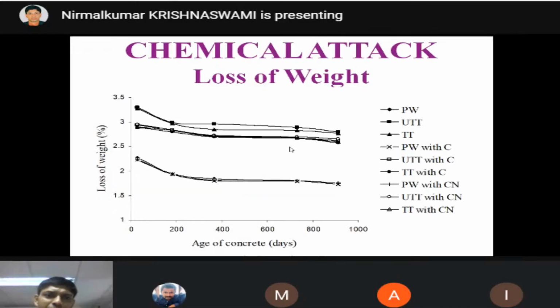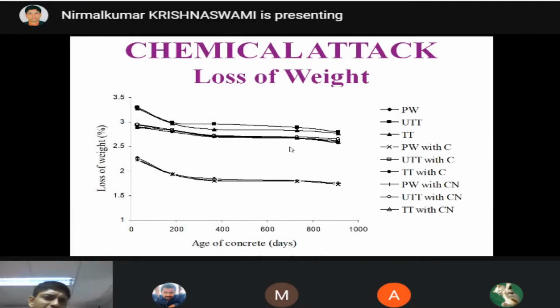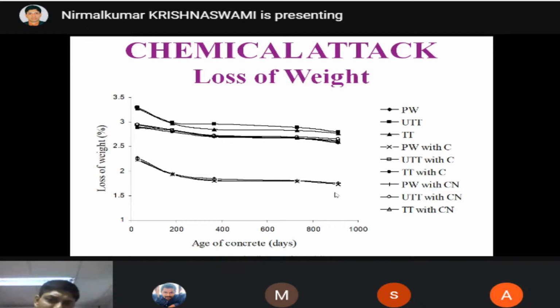And this is for the chemical attack. Here I used 3% diluted sulfuric acid. Then these are all the results. Loss of weight is very high because it is immersed in the acid solution for 28 days. Without adding the admixture, 3.5 percentage reduced, lowest around 3 percentage. But when we add the admixtures, it's reduced to 2 percentage. You have to observe that even by using the potable water, you'll be having the same kind of adverse effect. This you have to take into account.